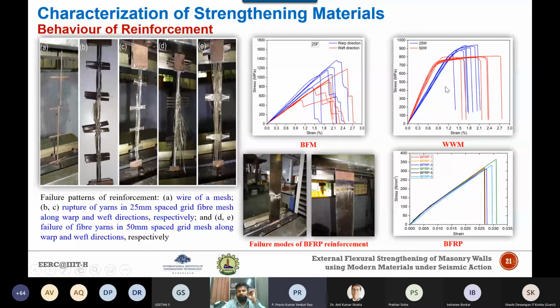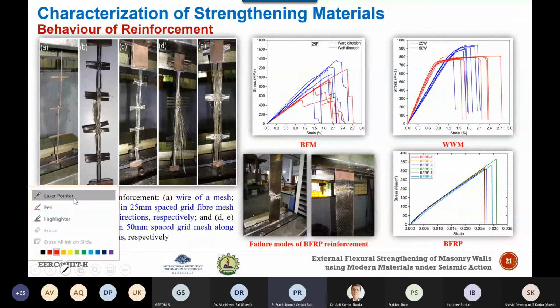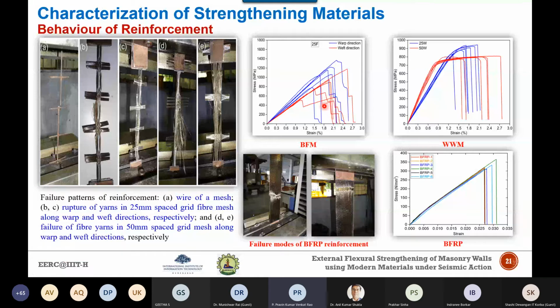Here in this curve, you can see, let me use the laser pointer. Here you can see that there is a sequential load drop and again a regain in the stress strain curve, especially for this basalt fiber mesh. So why is this happening? This is attributed to the progressive breaking of the individual fibers or yarns of a roving. And the difference in the mechanical properties in the warp and weft direction is due to the influence of the weaving process.